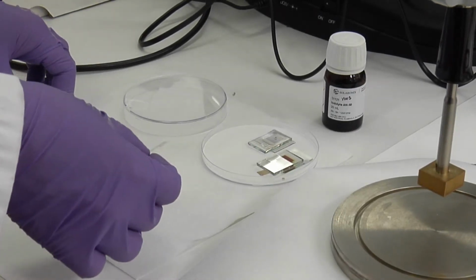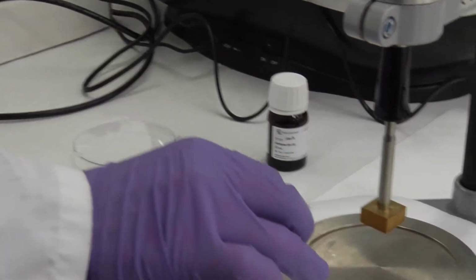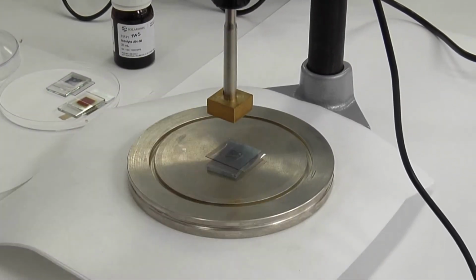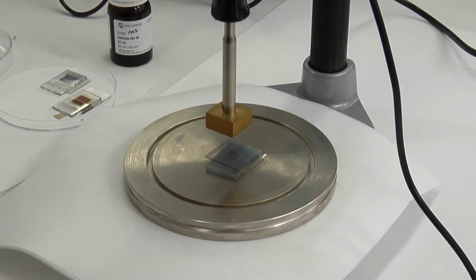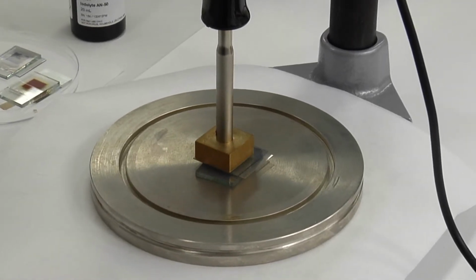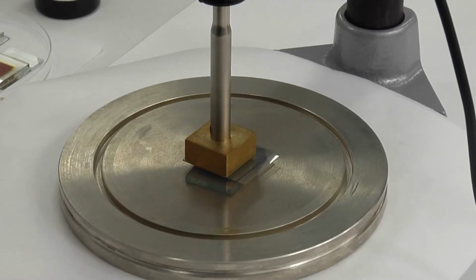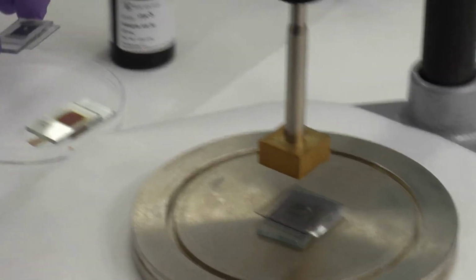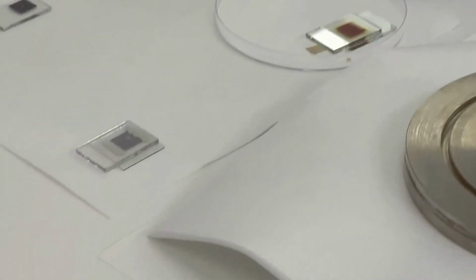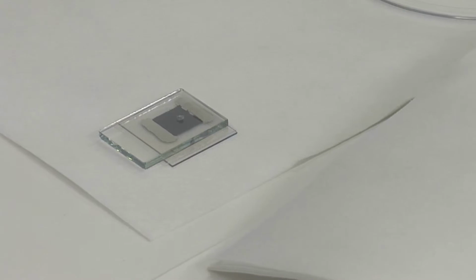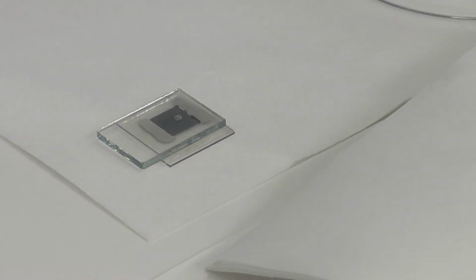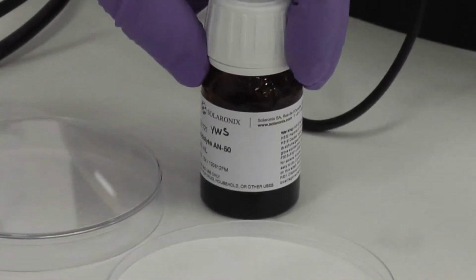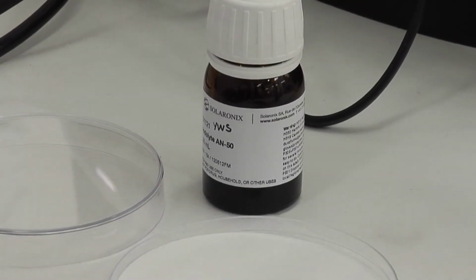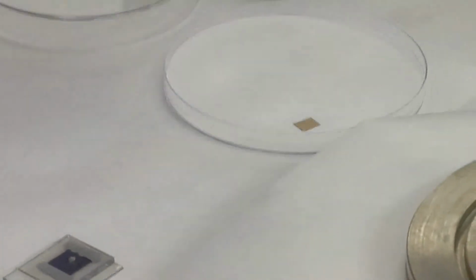and a polymer. These electrodes are sandwiched together by applying heat using this hot press. After applying heat, the polymer will seal the two electrodes together, and the product will look like this. And then we will inject the electrolyte, redox electrolyte, through the hole inside the device. And then we will seal the hole again with a polymer. And the final device will look like this.